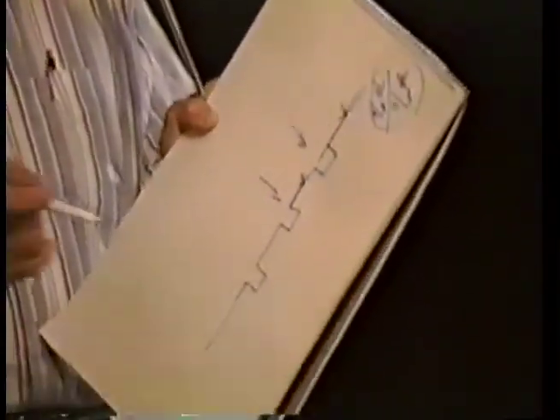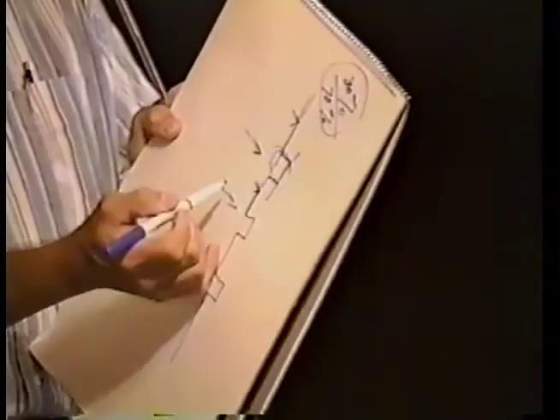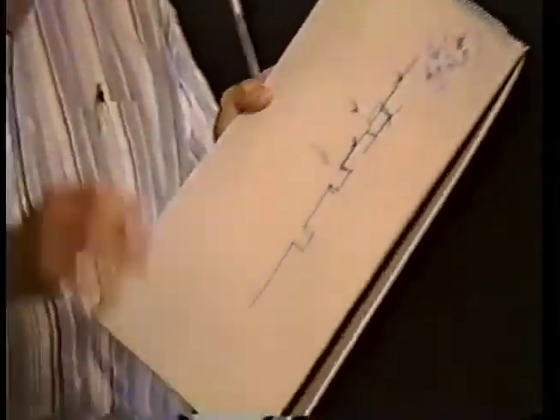With reverse current etching, you'll note that there's a lot of rounding, and if you can imagine how an Alka-Seltzer dissolves in water, it gets very ragged and rough. So when you talk about ring-bearing surface, there is less of a relationship between the real porosity and the ring-bearing surface than you would have if you're actually applying that porosity through some mechanical method, because you can control the depth, the size of the hole, and the sharpness of that hole itself. Those are your oil retention pockets, in addition to the microcracking that comes out of that chrome surface too.